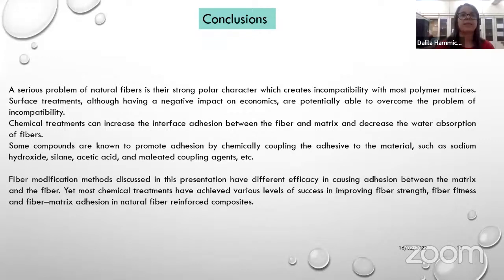As a conclusion, I can say that a serious problem of natural fibers is their strong polar character, which creates incompatibility with most polymer matrices. Surface treatments, despite having a negative impact on economics, are potentially able to overcome the problem of incompatibility. And chemical treatments can increase the interface adhesion between the fiber and matrix and decrease the water absorption, for example, of fibers. Some compounds are known to promote adhesion by chemically coupling the materials, such as sodium hydroxide, silane, acetic acid, and maleated coupling agents.